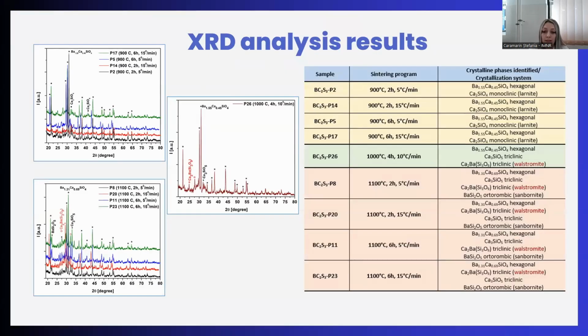And regarding the XRD results on the samples, for better understanding, we can look at the table. For the samples that were sintered at 900 Celsius degrees, we can see that the time and the heating rate have no influence. And in all of them, we identified 2 crystalline phases: a hexagonal phase of calcium and barium silicate, and the monoclinic phase of calcium silicate.